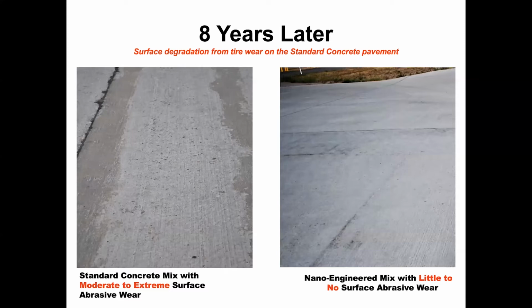And with that liquid fly ash, it allowed for extra pozzolanic reactivity, as an SCM, to maintain basically the same type of performance we were getting with the 7-bag mixes. Once again, I went out on my own, and we did this without wet cure. We did it without a cure compound. We basically put it down, used our bridge finish machine, struck it off, and then surface textured it with a tine, a typical roadway application, and we had very good luck with that.